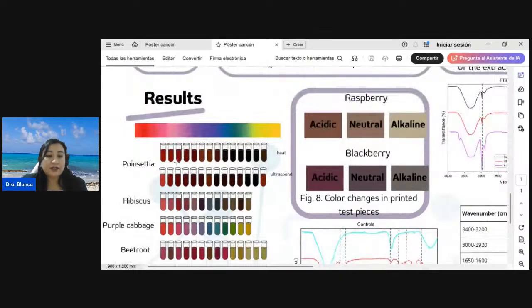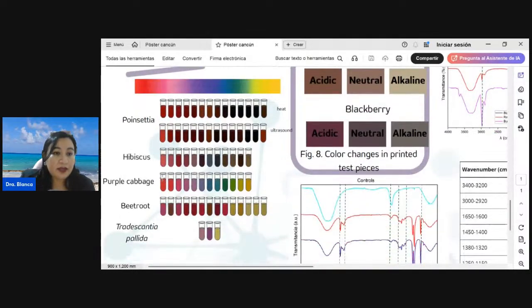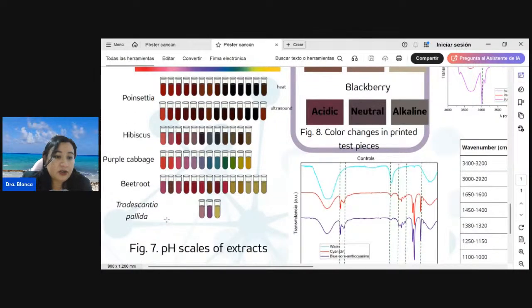now I will discuss the main results. First, we show the principal change with the pH measure for poinsettia, hibiscus, purple cabbage, beetroot, and Tradescantia pallida. One of the most important observations in this stage was the clear color response to pH change. The pH scales obtained demonstrate that several extracts exhibit noticeable chromatic transition between acid and alkaline environments. This confirms their potential as visual indicators, like we show in figure 7.